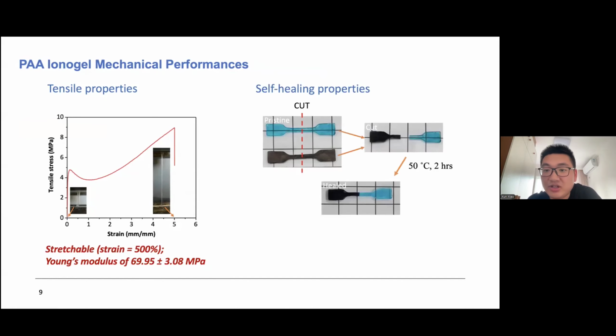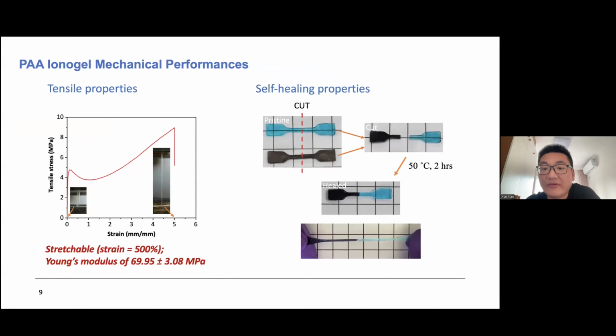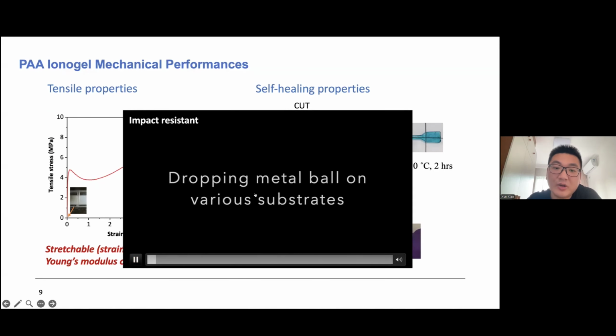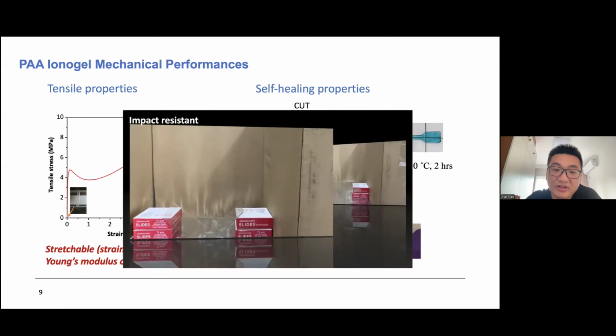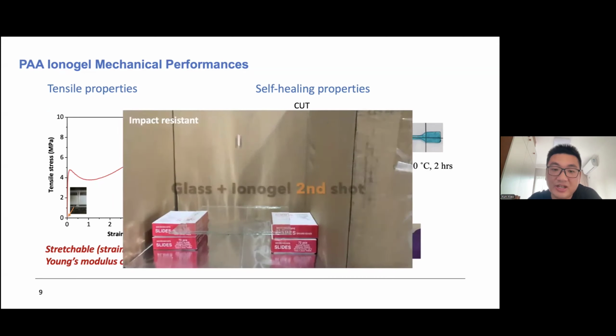So this is a demonstration of how we use the self-healing. We first cut two ionogel samples, then put them together and put them under 50 degrees C for 2 hours, and then it's self-healed. And if we use this self-healed sample, we can find it can be stretched again. To show how the PAA ionogel can be a very good mechanical improvement for our perovskite solar module, we can use this one. Usually we use glass for the encapsulant, and you can see the bare glass can be easily shattered into pieces.